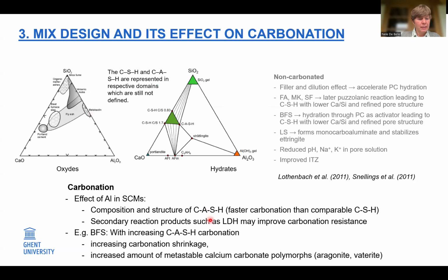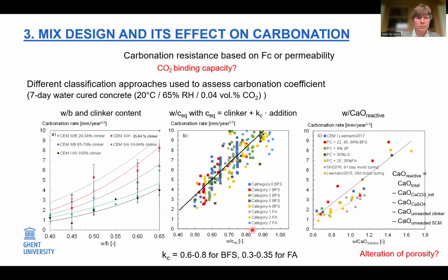Also, we see that the percentage of the calcium carbonate that is present as calcite is reduced, while we have an increased amount of the metastable aragonite and vaterite. And this might lead to a higher permeability. But on the other hand, there could be secondary reaction products, such as layered double hydroxides, which may improve carbonation resistance. But yeah, their effect is not yet fully understood.